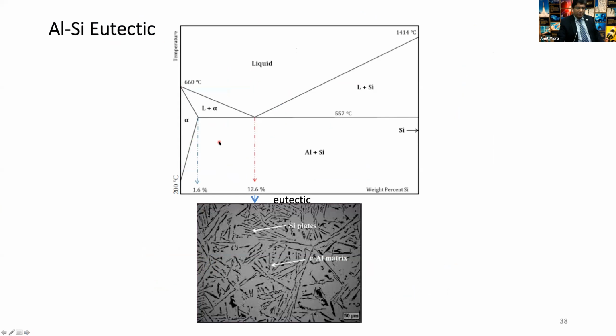So most of the undergraduate material science courses will introduce phase diagram, and one of the best, most common examples is aluminum silicon. The easiest phase diagram you can think of, eutectic. Aluminum and silicon do not mix. At room temperature, there is minimal silicon alloying in aluminum, and there's a eutectic at about 12.6%. And this eutectic has this discontinuous structure of silicon. It says plates here, actually it is more flake type structure. You see these discontinuous flakes that form. The scale is 50 micrometer. So very coarse structure, not very useful, not very high strength.